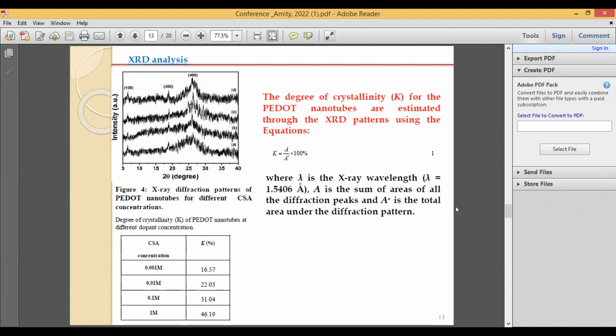So, how did you calculate the crystallinity? Actually, we have taken the total area. So you have fitted the curve in Origin first, and then you calculate the total area. So you choose the whole scan area. And we have supposed that in our case the 3 small peaks are there. So we calculate the area of the 3 peaks, then divide it by the total area of the whole diffraction pattern. So I think it's just a rough estimation.